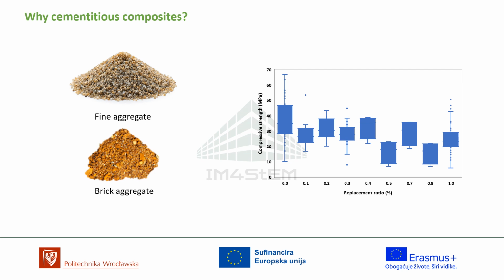When we look, for example, at another option, replacing fine natural aggregate with fine brick aggregate, it yields very promising results in terms of, for example, compressive strength. In various compressive strength tests done around the whole world, with results gathered from the literature survey, the fine brick particles sometimes stay at the same level as the reference mixture or in some examples even exhibit higher strength. Although it has to be pointed out that in many cases the reference mixtures were different themselves. So these results are only preliminary.